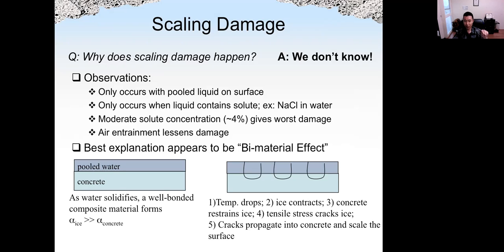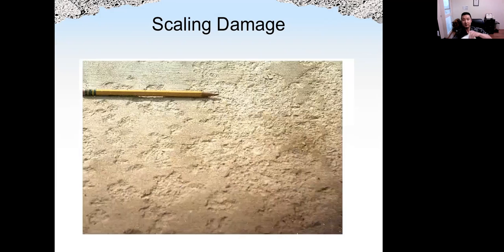And the crack will somehow propagate into the concrete layer, but not very deep into the concrete, so only the top surface of the concrete. So when a crack is generated in the ice layer, sometimes the crack will propagate into the concrete layer. So that's why we have this scaling damage, only limited to the surface of the concrete. And we can see here, this is caused by the scaling damage, and the damage is only limited to several millimeters inside the concrete, so not very deep.